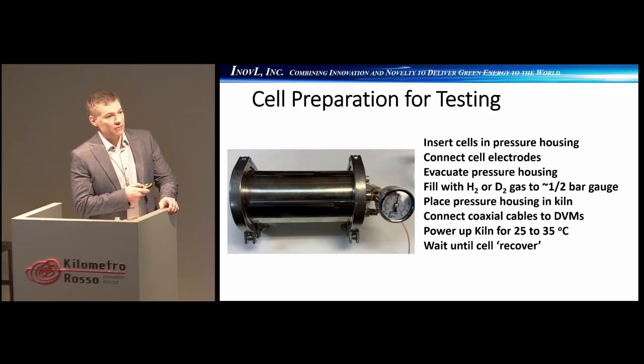We then take our vessel and we run extended vacuum on it. And the reason we run the extended vacuum is because water is not your friend. So you really have to do a hard vacuum. And then we will refill and back and forth several times. After we do that, the cell is usually not very happy. So we put it in the kiln, then we put it about 25 to 35 degrees Celsius, and we wait for it to recover. And this can be a few hours, up to 8 to 36 hours to several days.